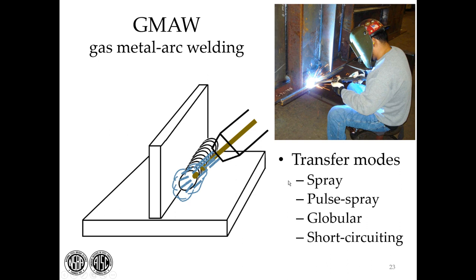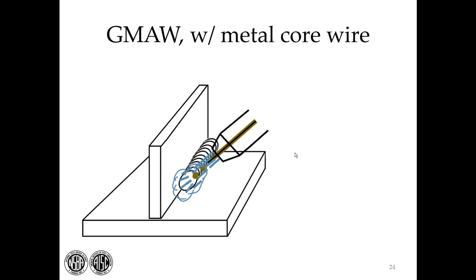Another thing to note about this process and the ones we've discussed so far is that we call them open arc processes. In other words, if you see the welder welding as is shown here, you can see the arc. You don't want to look at it with your bare eyes. You'll damage your eyes. So welders always wear shields when they're using the open arc. Another variety of gas metal arc welding is gas metal arc welding with a metal core wire. In this particular case, you'll see that there is a core, but it's not a flux as in a flux core, but actually other constituents. Those constituents will be used to help build the weld more efficiently, or you might add alloy to change the characteristics of the weld.